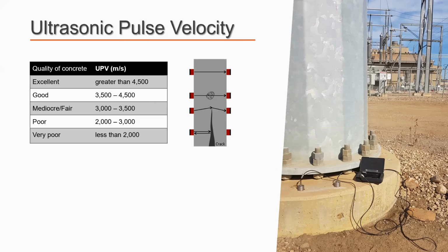So if you measure the velocity and it is a higher velocity, you might conclude that this has good quality. Now, to have meaningful results, you have to avoid putting your probes over the steel reinforcement. So it's always good to use a device to find the approximate location of rebar, to avoid direct placement of sensors on the reinforcement as much as possible.